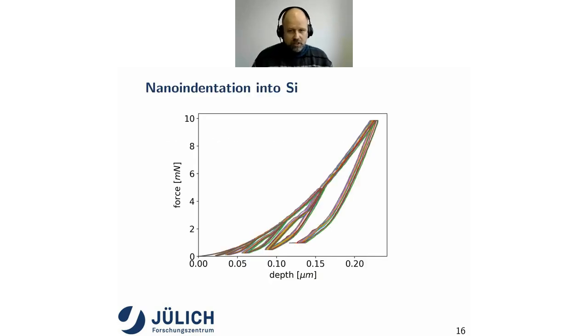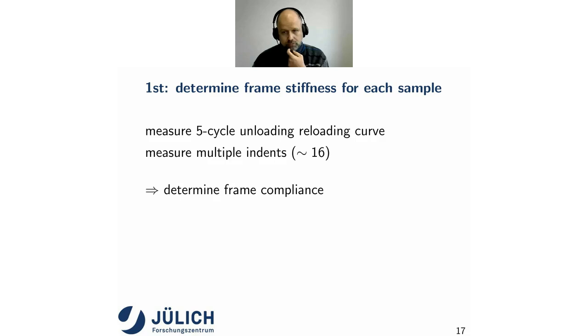Once we know the contact area, we can use nanoindentation analytics to determine everything like Young's modulus and hardness. So this is a curve that we typically use. We load and unload 5 times with increasing force. So load, unload, load, unload, load, unload, and so on. And we use these 5 unloading cycles to determine the frame stiffness for each sample that we use. So let's say we have 5 unloading cycles and 16 indents or 16 measurements, and we have roughly 80 unloading cycles, which we then can use to determine the frame compliance for this specific sample.